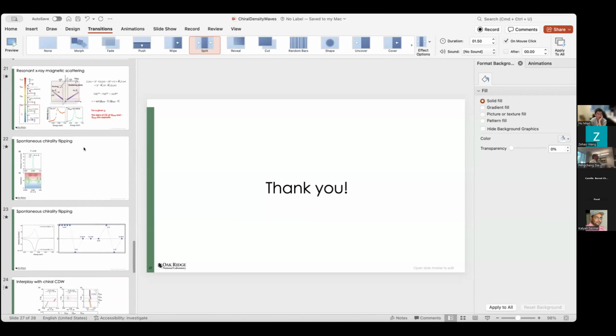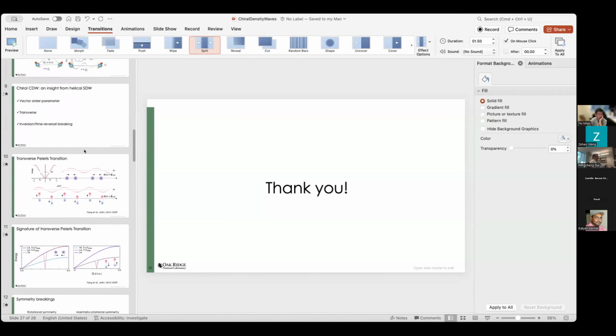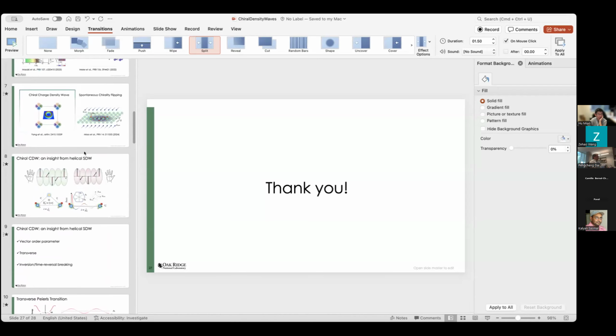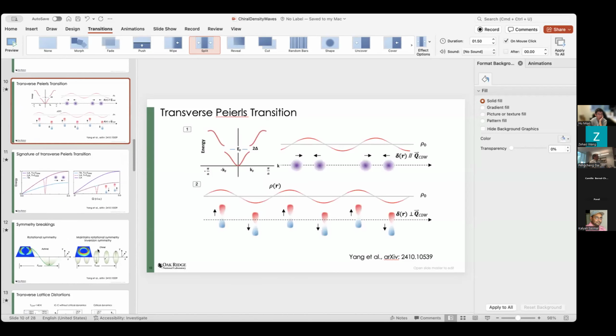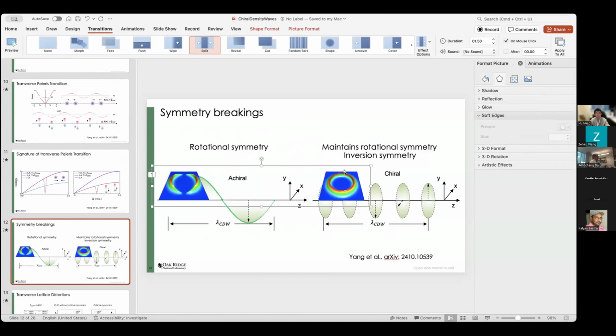Yes. So let me go back to the cartoon. No, actually this one. So assuming these vectors indicate the lattice displacement direction, you can imagine this is the c-axis. Let's say one aluminum layer is displaced up, and the next layer has a 90-degree rotation and goes down, and then another 90-degree rotation. So the lattice distortion forms a chiral structure. So that's what I mean by chiral CDW.